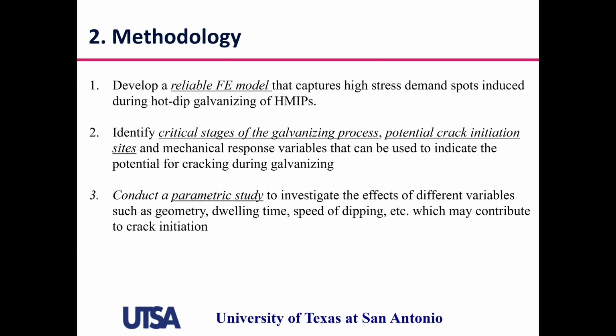And our methodology has consisted first of developing a reliable finite element model that can capture the high stress demand spots induced during the hot dip galvanizing. And actually, it is important to develop a model because there's very little that we can track experimentally, because the temperatures of the hot dip zinc bath are in the order of 800 Fahrenheit. So strain gauges actually melt. So it's very hard to track the behavior of the structure during galvanizing. So the models have become a great tool to study these structures.